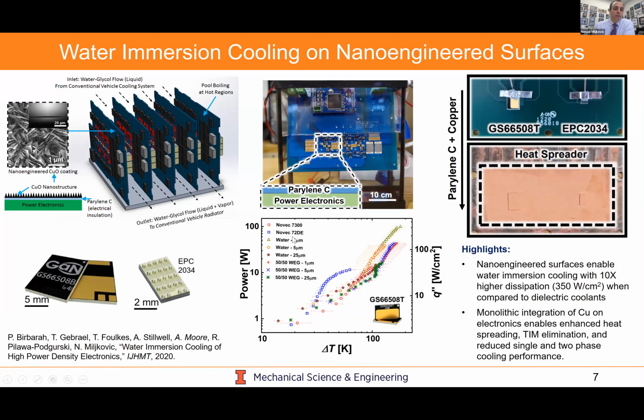And you'll notice that the Novec dielectric fluid, which is a common immersion fluid currently used, can really get you only on the order of 35 watts per centimeter squared. Now, if you were to shift to water with a thin enough Parylene coating, you could reach all the way up to 350, which has huge implications for power densification. So from this point, we've moved on.